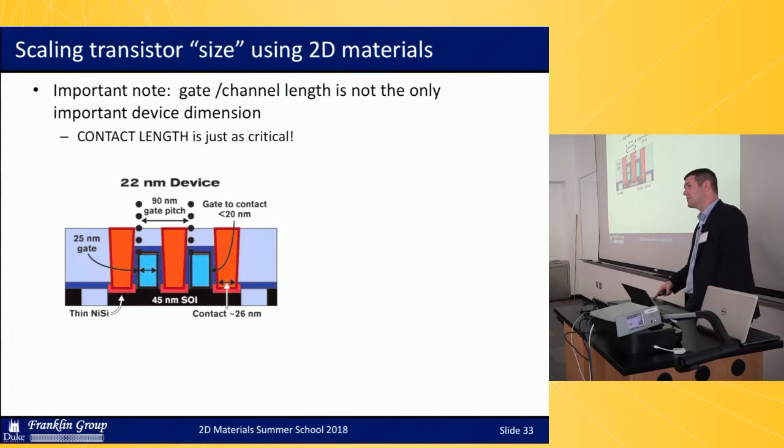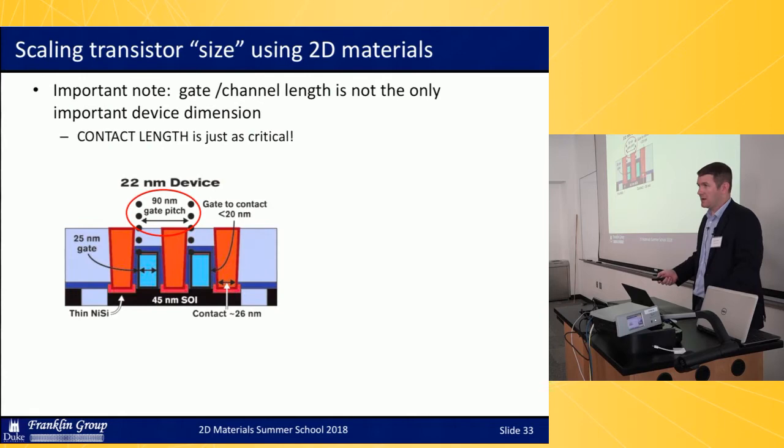And that contacted gate pitch is something that swallows up both a channel and a contact length. And so the length of the contact matters just as much. Well, you may not realize that when it comes to silicon devices, that contact length, which is seen as the full contact plug in this cross-sectional picture here, is a significant scaling bottleneck, even for silicon, because you end up